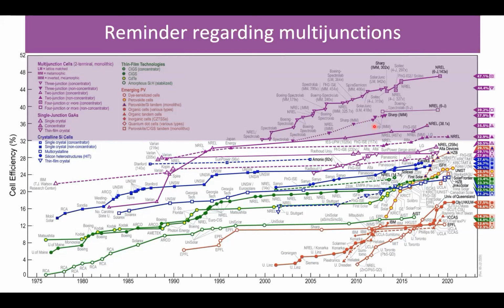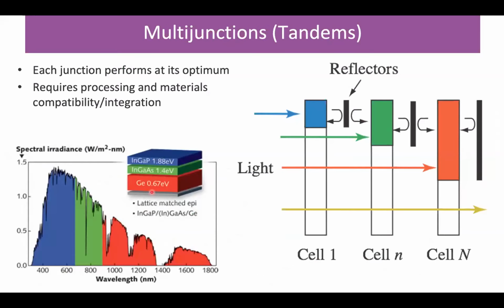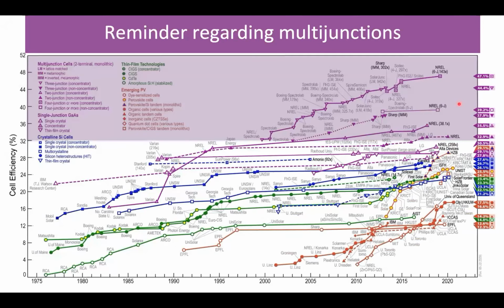And so, you jack up your complexity, and you have to pay more costs and more expenses, particularly when it comes to materials like I highlighted here, which, while they're awesome PV materials, on a per square meter basis, if you can afford a Bugatti, you could afford the kind of PV that has a triple or quadruple junction, with power conversion efficiencies up in these 40% regimes. And it turns out if you're the NSA and you want to fly a satellite, that's actually a pretty good deal. But for most residential homeowners, it turns out that's maybe out of reach. I guess that's the right way to say it.